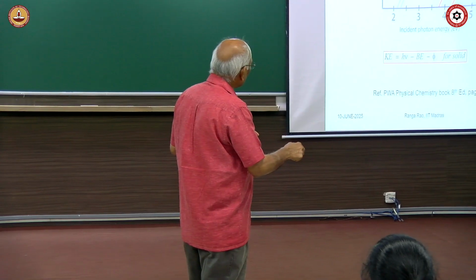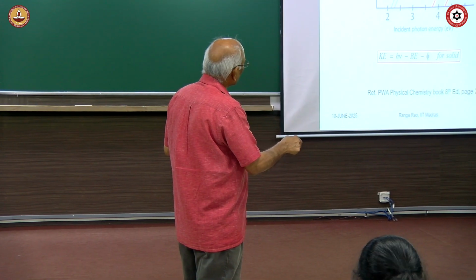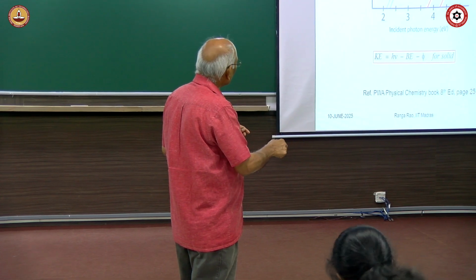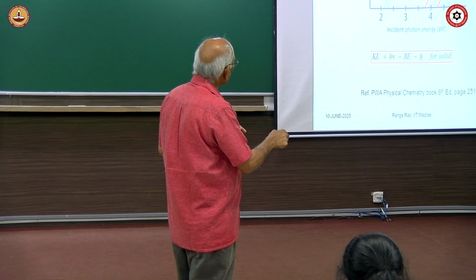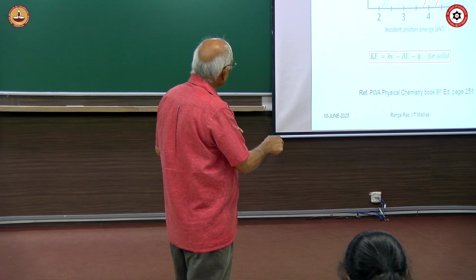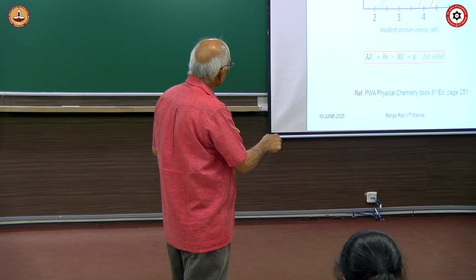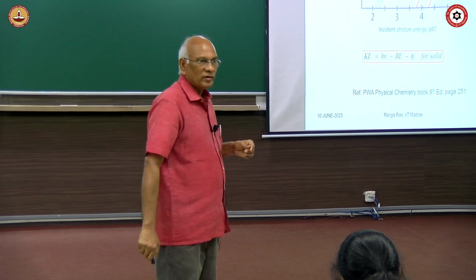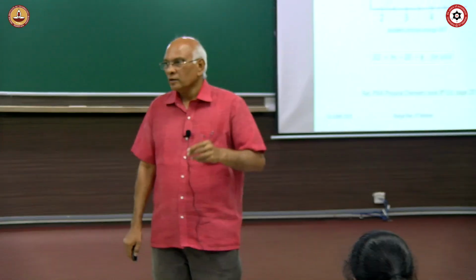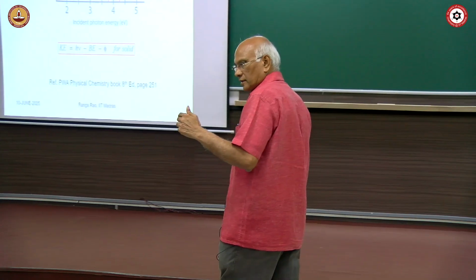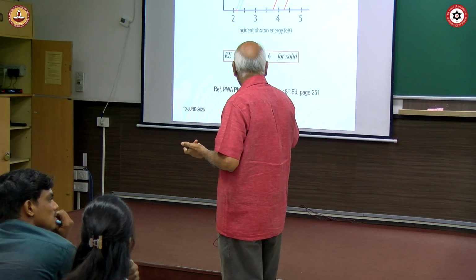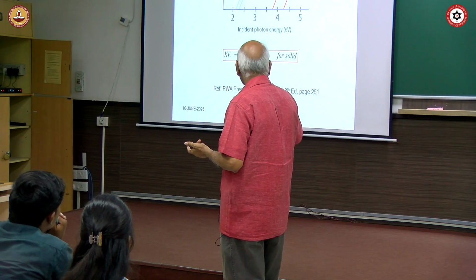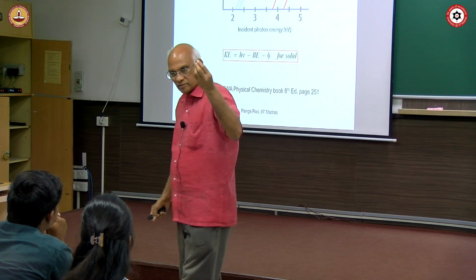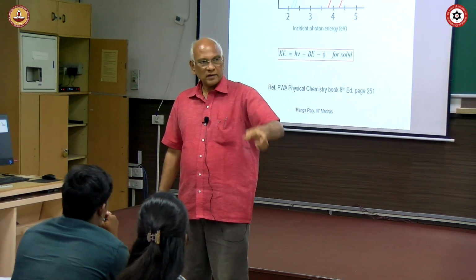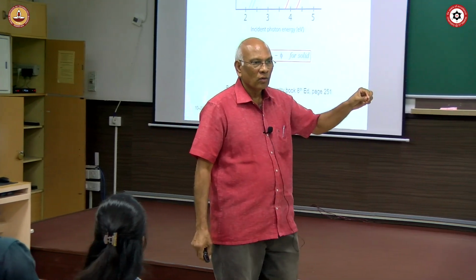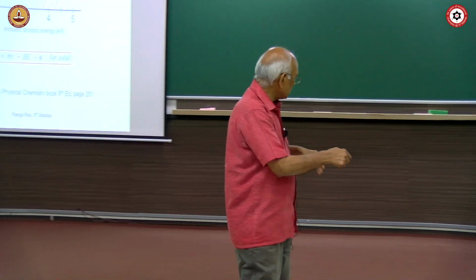At this frequency and beyond, you start seeing photoelectrons coming out from silver. Whereas you don't need this much energy for potassium or lithium. For lithium and potassium, you see it is only very small, about 2.1, 2.3, 2.5. You need only 2.5 electron volts of light to get the photoelectrons out. So the threshold frequency is very low here. That means potassium and lithium are very easy to ionize. Ionization potential, do you remember? Alkali metals, ionization potentials are very low,